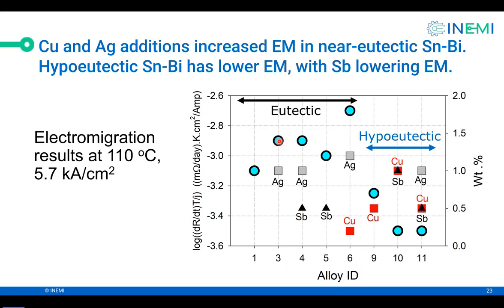Alloy 3, the rate of electromigration is higher because of silver addition. Alloy 4, the rate of electromigration is higher because of silver addition, and there's also some antimony in it. So maybe the silver dominates the role of antimony. Now let's go to alloy 5. The rate of electromigration is -3, a little less than when silver was there. It has come down because there's no silver, only antimony here. If I look at alloys 4 and 5, and if I trust these results, this is saying that silver dominates the electromigration in eutectic tin bismuth more than antimony. So antimony plays a lesser role.